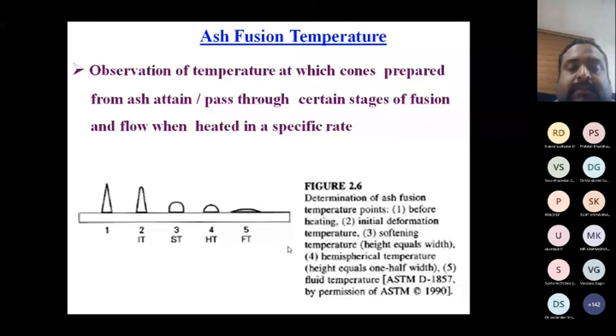Observation of temperature at which cones are prepared from the ash. When it is heated, it passes different stages of fusion or flow at a specific rate. For example, this is an ash cone, a raw cone prepared from the biomass ash. When it is heated, initially the tip melts. That's called IDT, initial deformation temperature. That is the first one.